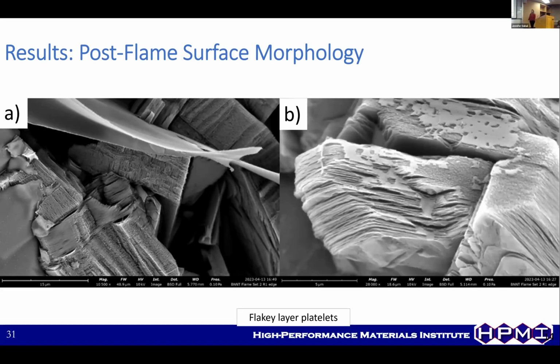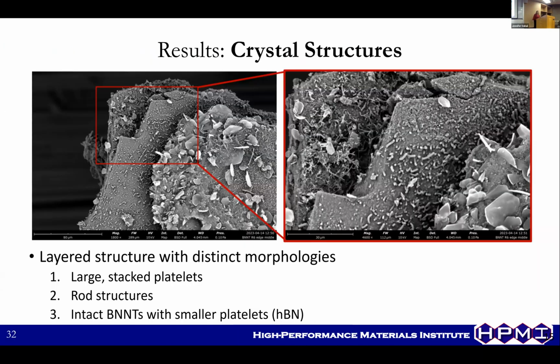And further studies of this flaky layer: the platelets are really very large, like full flaky layers. And if you've ever seen SEM of rose gypsum, it looks kind of like that, but that's clearly not what that is. So we have a layered structure with these distinct morphologies: large stacked platelets, rod structures, and intact BNNTs with smaller hBN platelets.